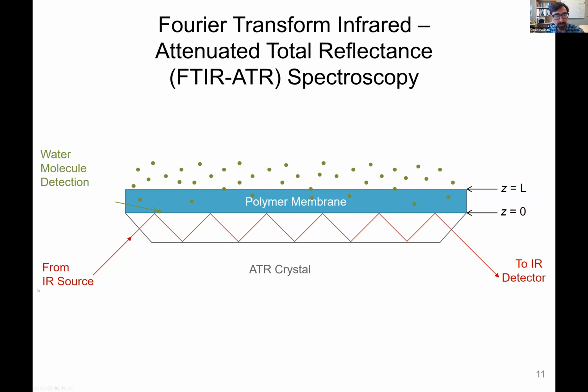So we have an infrared source, just like infrared spectroscopy, like you might use to determine the chemical composition of a material. It enters a high refractive index crystal, an attenuated total reflectance crystal, and it can have single reflection or multiple reflections, but then it exits the crystal and goes to the detector. And at each of the reflections, there is an evanescent wave that can actually detect and interact with the sample.